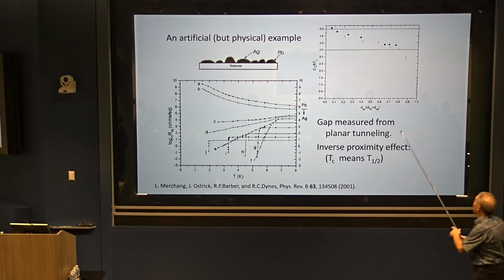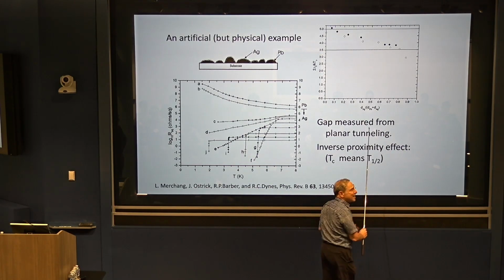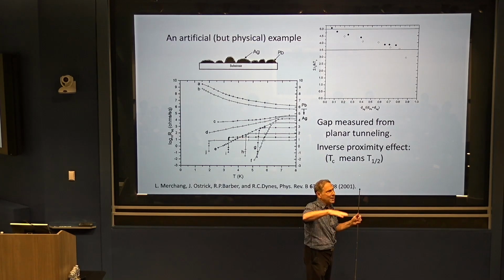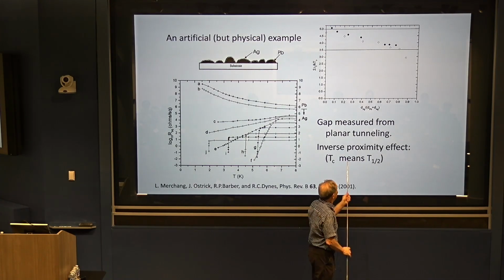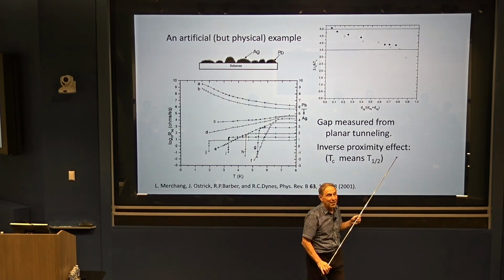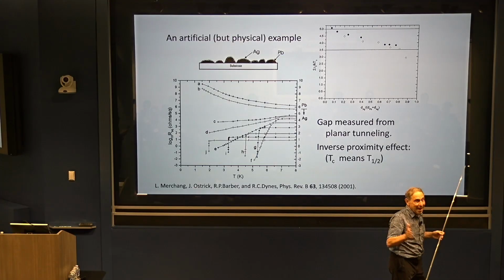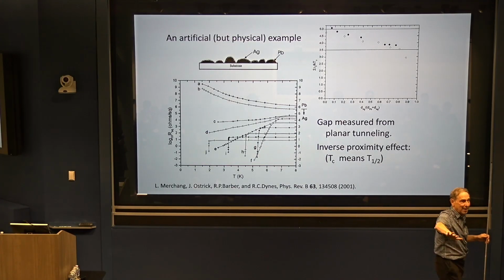Just for those who don't know, basically what this says is that if the electrons are delocalized between the silver and the lead, then it feels an attractive interaction only for the fraction of time that it's in the lead. So lambda gets scaled by the fraction of the system that's lead. And that physics is very simple in the Cooper limit.